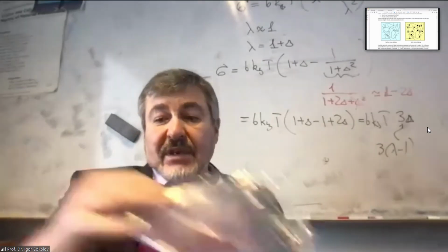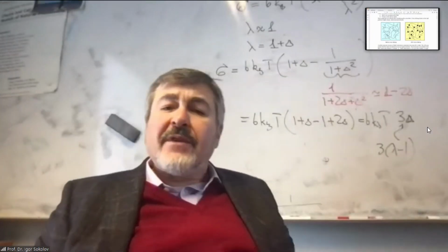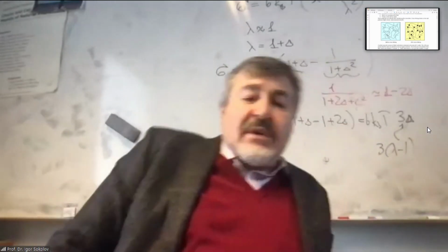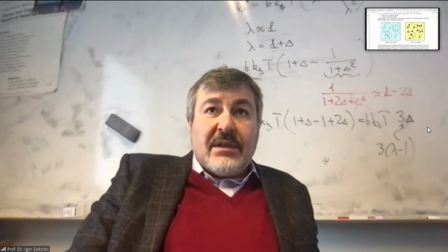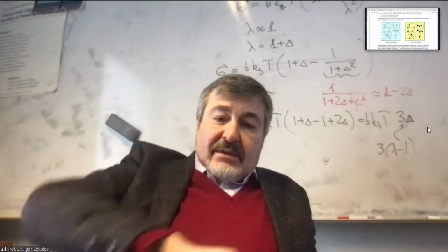But it's different, not very, but still different from the irreversible deformation in a solid. It flows, it's a fluid. Because in a solid, you go into the regime of plasticity, you form, and then it stays in the form.